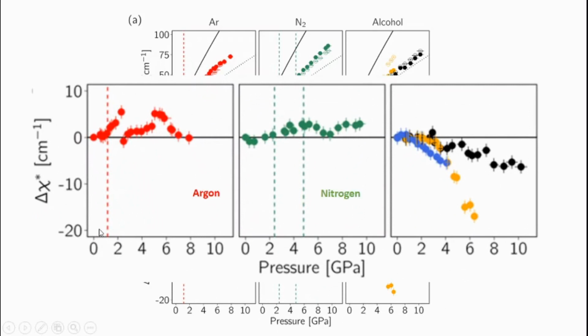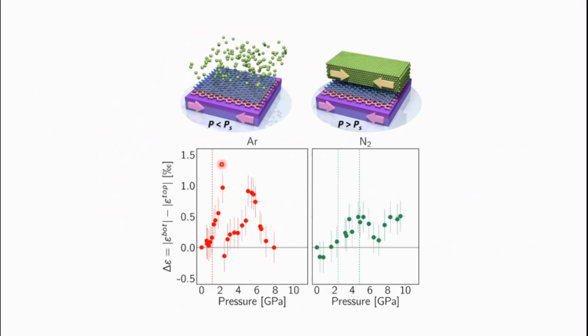Argon and nitrogen are two inert media, and we only expect mechanical effects. We observe that the variation of chi is always positive and shows in particular important changes at the solidification or solid-solid transitions of the media, shown as vertical discontinuous lines. This can be evaluated as a strain difference between the two graphene layers, which is 0 when the pressure transmitting medium is a fluid, and becomes non-zero when the bilayer graphene system finds itself sandwiched between two media of different compressibilities. The differences in the mechanical solicitation slightly decouple the two graphene layers.